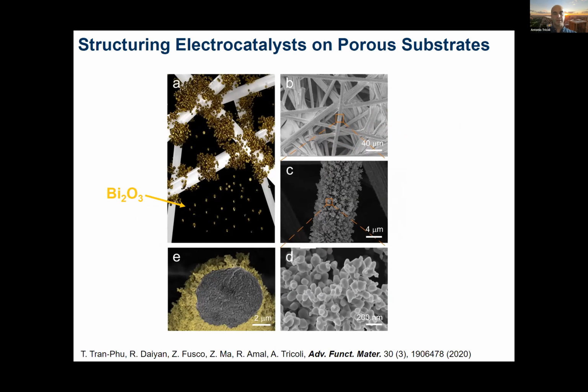Now, another thing I wanted to discuss is the feasibility of using approaches such as flame synthesis not to coat only flat substrate, but to coat porous materials. This is an example of a structuring electrocatalyst, such as bismuth oxide made by flame, onto porous carbon fibers. And what happens here is that once we start using aerosol deposition, the nanoparticles reach a boundary layer around the material and then start moving by diffusion and Brownian motion. The beauty of this is because the aerosol is uniform, it will uniformly coat around these fibers. And you can see here that the same structure I showed you before can actually grow around a carbon fiber and form a very nice porous fractal structure.